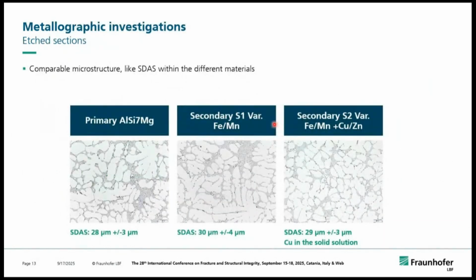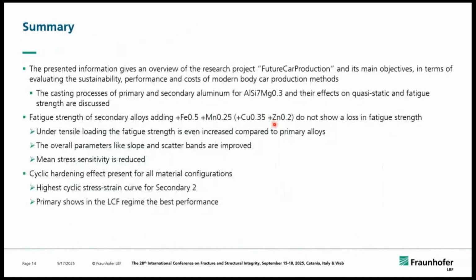When we look a bit into the microstructure, we made some evaluations, or more precisely the colleagues in Munich did, and when we compare those results, we have the aluminium and the silicon in the 2 main phases. The copper in the secondary 2 alloy is somehow incorporated as a solid solution phase in the matrix. And when it comes to the secondary dendrite arm spacing, it was not really surprising. The values were comparable. And usually the secondary dendrite arm spacing, more precisely, is the value that we somehow try to use for a comparison to the fatigue strength. Since we see not really a large difference in the secondary dendrite arm spacing and not in the fatigue strength, this somehow matches once again, also for those primary and secondary alloys, with what we know from literature.